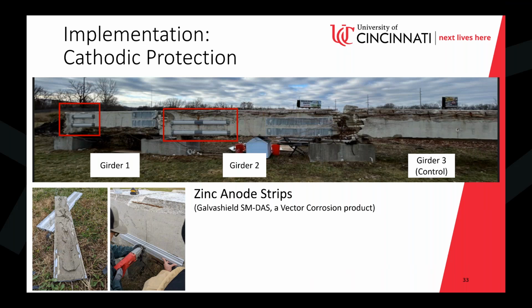The other product, instead of pasting on the zinc metal and having the zinc metal exposed on the outside, is more similar to if you had pre-installed cathodic protection, say in a large infrastructure product. Typically, if you have zinc anodes embedded in the concrete, what this is, we're going to extend the girder effectively by putting zinc anodes in a grout, which is going to act like that concrete and still conduct the ions. But everything's basically contained in a strip here. So you apply the grout, you mechanically mount it to the surface of the girder, attach a wire again to the steel in the girder somehow, and that's the installation setup. Relatively quick and easy, and really mimics the kind of pre-installed cathodic protection you can see in some large infrastructure products. So those are the two things we mounted.